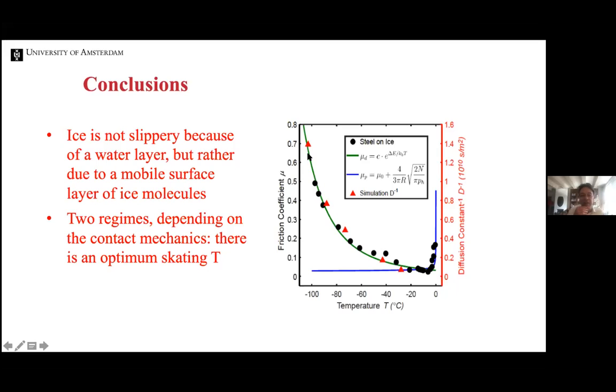Perhaps the most interesting finding is that if you measure the friction over a large temperature domain, you get a minimum somewhere right around -7. That is the optimum skating temperature. And if you ask the ice master of the great skating rink in Holland, Thialf, what the fastest ice temperature is, he says he always keeps the ice at -7 because that's where the lowest skating times at different distances are reached. The ice master already knew that, but now we actually understand why that happens.